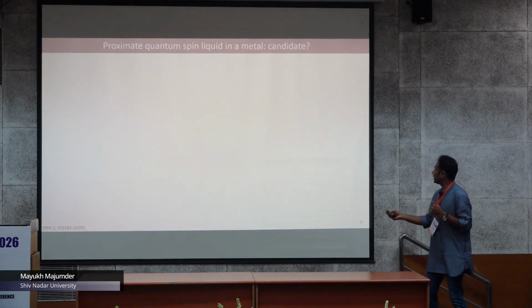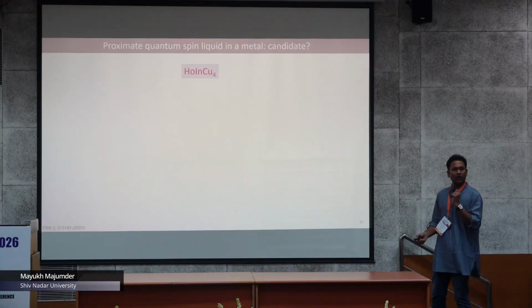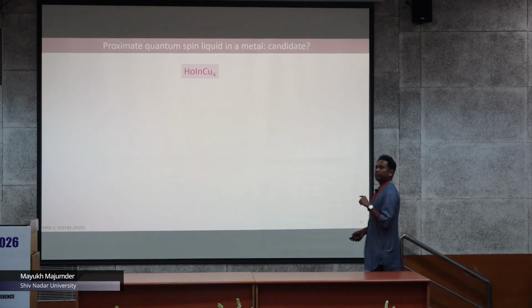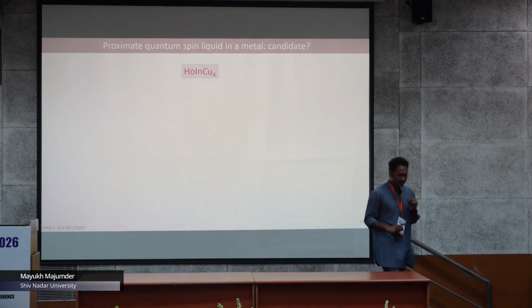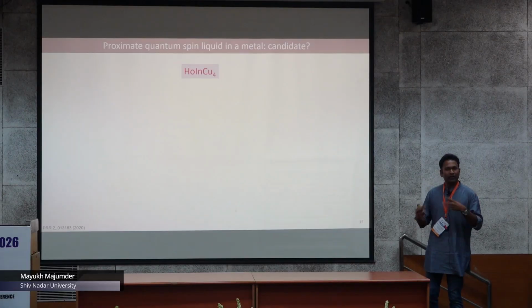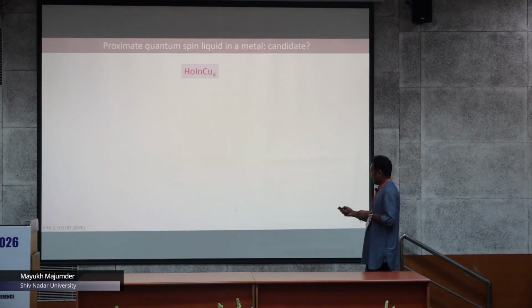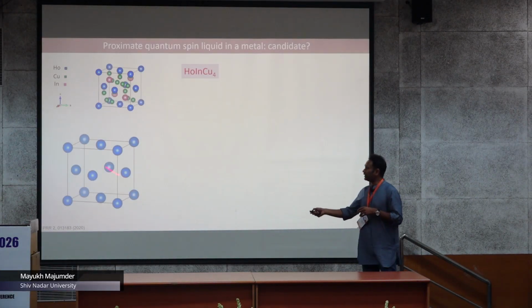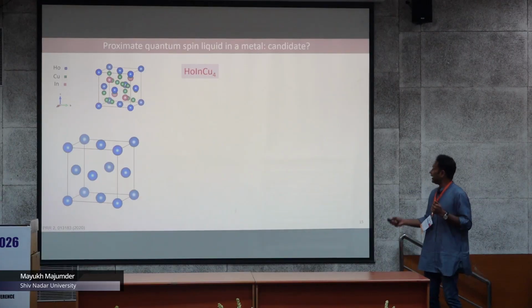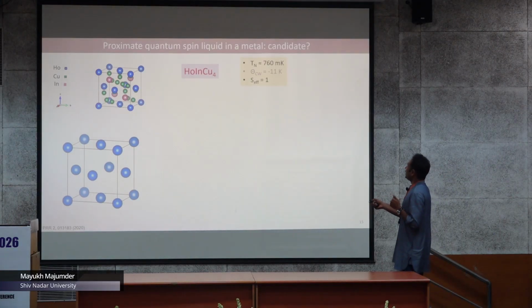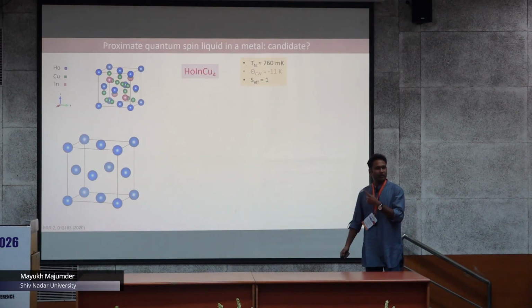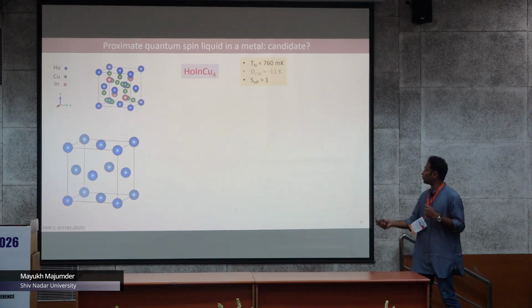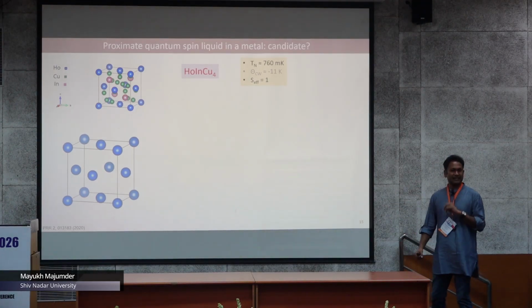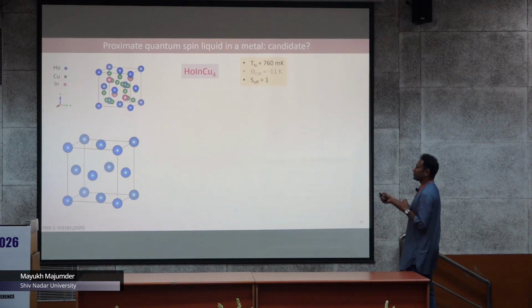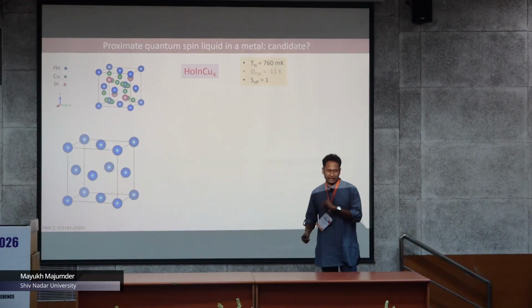So now this is our intention, and so we actually looked around several compounds and found this holmium indium copper 4, where copper is non-magnetic and holmium is a non-Kramers ion, and has magnetism there. And the holmium moments are sort of forming an FCC lattice. Okay, and what was known is that the ordering temperature, or the phase transition temperature, for this particular compound was 760 millikelvin. The Curie-Weiss theta was found to be minus 11 Kelvin.